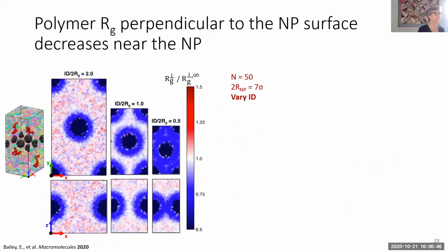Okay, so we're going to start with chain conformation. And so this is the top-down view, right? And so this is the surface of that particle, the surface of this particle, that's the interparticle distance. And then this is the side view, right? Okay, so the blue tells us that the chain is a little bit collapsed. And so this is the perpendicular component of the radius of gyration normalized by the bulk. And the only thing that we're changing here, it's all the same molecular weight, it's all the same particle size, we're just varying how far apart the particles are.